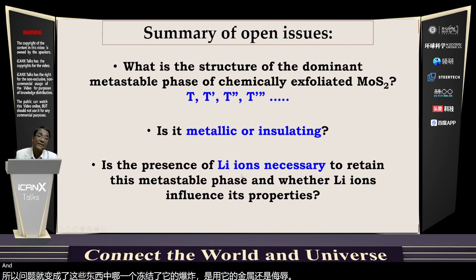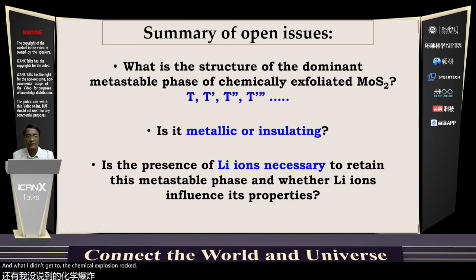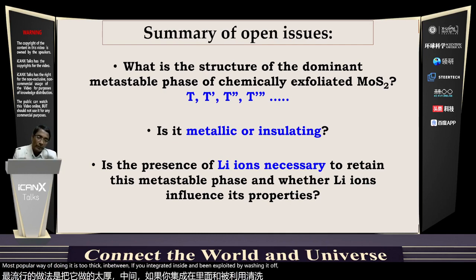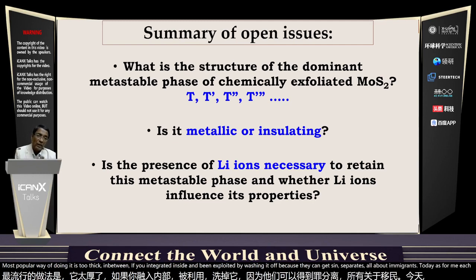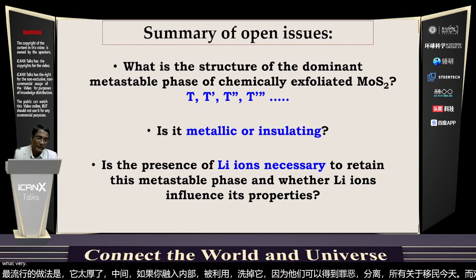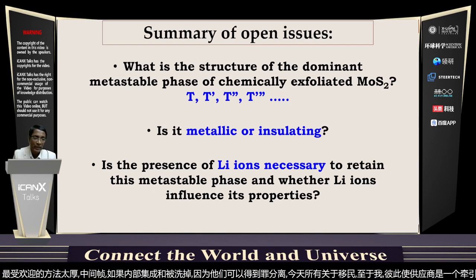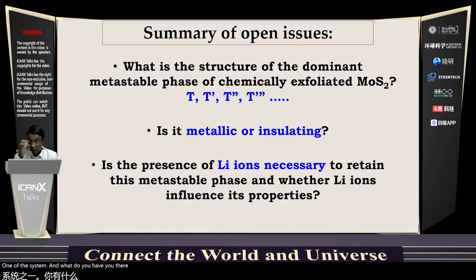And what I didn't tell you, the chemical exfoliation process, I'll not deal with that for too long. Most popular way of doing it is to take N-butyl lithium, intercalate it inside, and then exfoliate it by washing it off, because lithium gets in, separates out the MoS2 layers from each other, makes the van der Waals interaction even weaker, then it falls apart very easily. And then you wash it off to get rid of the lithium ions from the system, and what you have is few layer MoS2. And that's how you prepare the chemically exfoliated one.